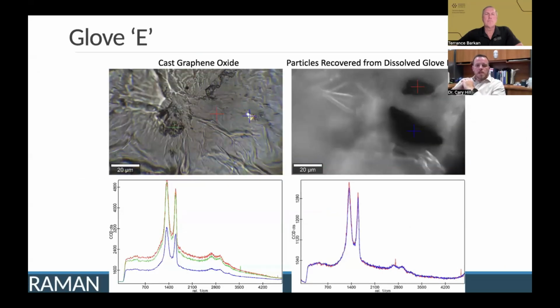And then glove E, this is the one that actually did test positive for graphene. We did get a verification opportunity, a sample of the graphene oxide slurry that was used in the production process. We performed our analysis first on the glove itself and then procured that sample so that we could do compositional verification. And sure enough, we found a match, a close match.